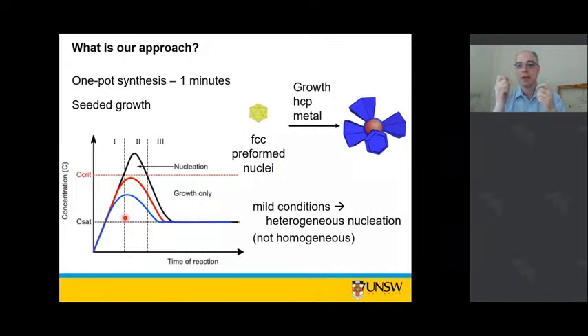If you have too high a concentration of the ruthenium zero valent atoms, you'll cross your critical concentration. The ruthenium atoms will start to bump into each other. You'll start getting nucleation, and then instead of getting your core shell structures and your branch structures, you'll end up just with a mixture of gold nuclei seeds and ruthenium nanoparticles.